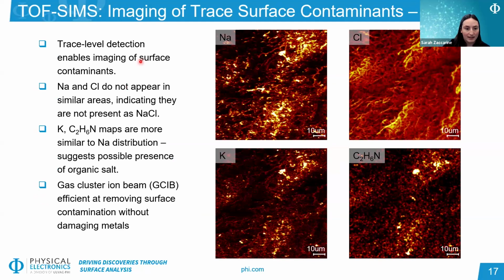So again, we're looking at this platinum nickel nanowire to start with, and we can also use this technique because it has trace level detection and it can look at more organic type molecular species. We're able to look a little bit more closely at the type of surface contamination we have present. So this is one example of these nanowires after synthesis, starting with sodium. We see a little bit of this tracking with certain nanowire type features. However, we also see that there's more globular presence that's different from the nanowire structure.